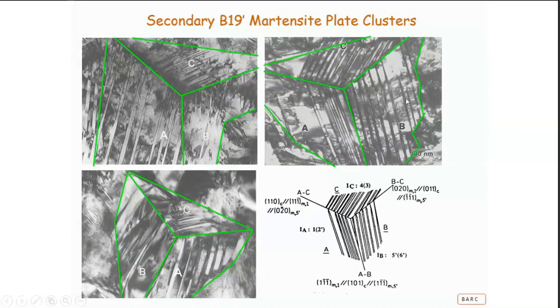And you see martensites without this feature because those are cases where you don't require the shear in order to meet that condition which I said is invariant plane strain. So you see this substructure within this martensite. All in all, you see three variants getting together, and you can see this substructure helps you to identify the orientation of the plate, and these three plates come together and give you a three variant cluster. And so that's the case of the B19 martensite.